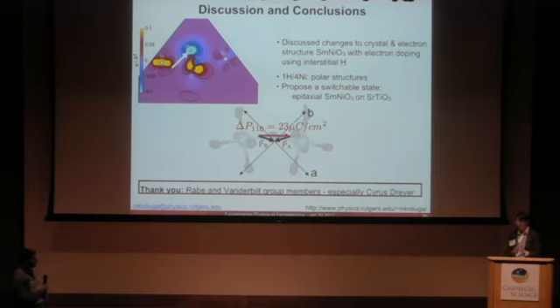Often experimentally, they do this around, I want to say, like 100 Fahrenheit. So the metal insulator transition of samarium nickelate happens at around 104 Celsius. So they do this doping below that transition. But then once you've intercalated the hydrogen, it is stable in ambient conditions. Also, they've tuned, I think, the growing conditions for the samarium nickelate to have these films that exhibit a good metal insulator transition and are switchable. And I forgot to mention, the experimental motivation and the group we've been working with on samarium nickelate is the Ramanathan group at Purdue.